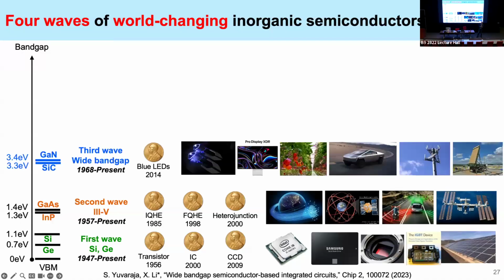The third wave is the wide bandgap semiconductors, represented by gallium nitride and silicon carbide. The research of wide bandgap started in 1968 when researchers studied the first epitaxy of gallium nitride. Right? And gallium nitride has a much larger bandgap compared to 3-5 semiconductors. And actually, that bandgap moved it right into the visible range. And because gallium nitride also has a direct bandgap, researchers can make it into very efficient blue LEDs. And nowadays, as we are sitting in this room, most of the lighting and also this display are based on blue LEDs. And as a result, the inventors of the blue LED received the Nobel Prize in Physics in 2014, and one of them, Shuji Nakamura, has visited KAUST multiple times.